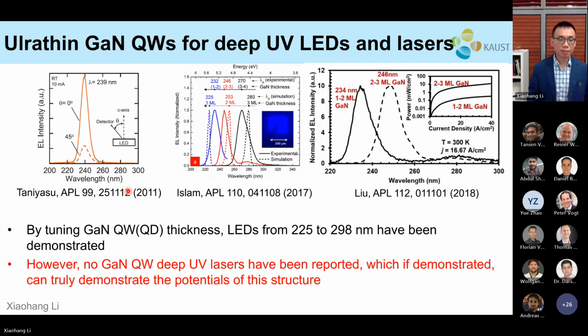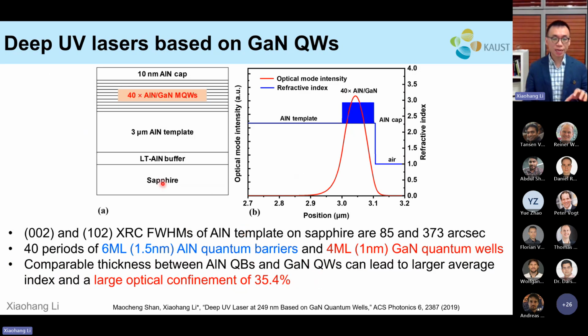So this idea is not new. Before our work, multiple groups in Japan and the US have demonstrated the use of ultra-thin gallium nitride quantum wells for deep UV LEDs, as you can see here. They can push the wavelengths down to 220 to 240 nanometers. However, there was no report of gallium nitride quantum wells for deep UV lasers. If we can demonstrate it, it can truly show the potential of this system for future UVC devices. So we decided to give it a try.